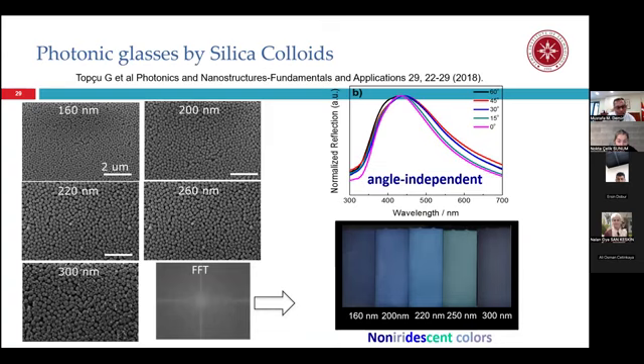So the electron microscopy images of the silica particles show the size lies between 160 to 300 nanometers. We are in the safe range for coloration. So in FFT, we don't see bright spots. That means the particles are not well ordered. They may be quasi-ordered or disordered.